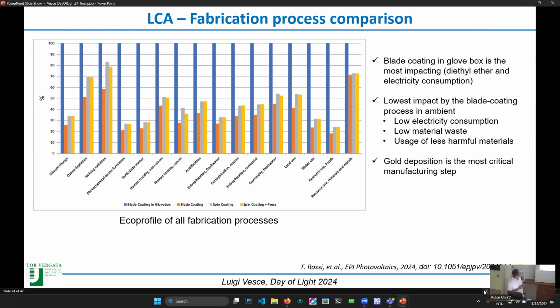According to the colors, with the blue you have the blade coating in glove box, and for example in orange you have the blade coating in ambient air. You can see that the blade coating in glove box is the most impacting process, if we take 100% impact for the worst case as a reference. This is because of the anti-solvent that they use, diethyl ether, which is really not a good material from an environmental point of view, and also the electricity consumption of a glove box. That's why, if you want something like a pilot line or similar, it's better to work outside the glove box.